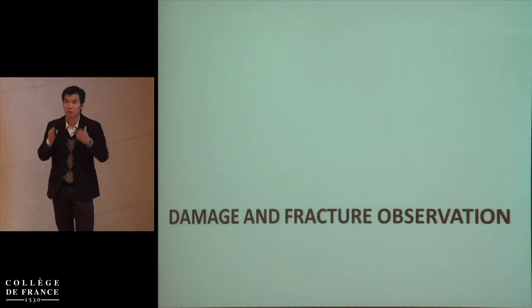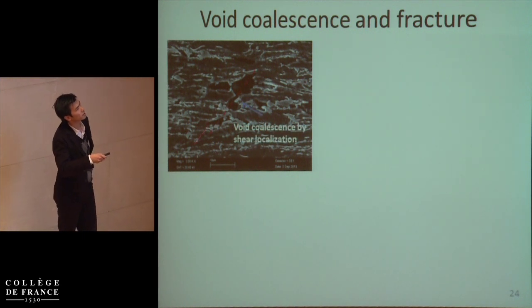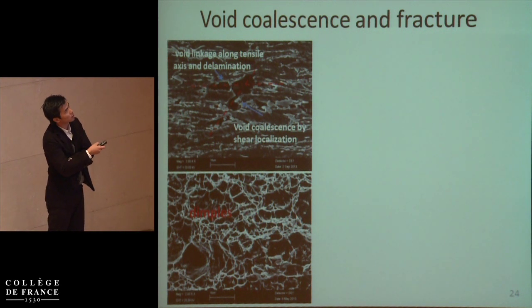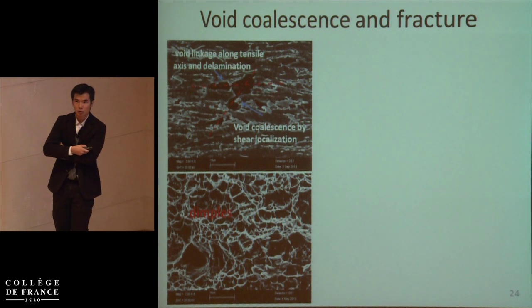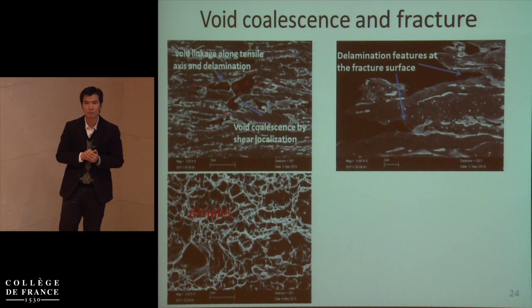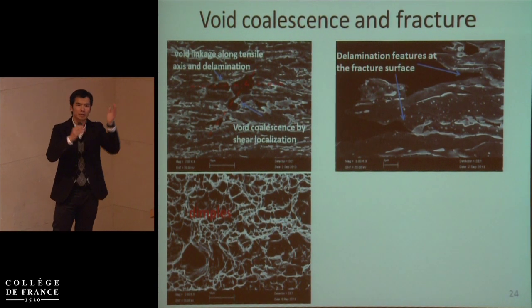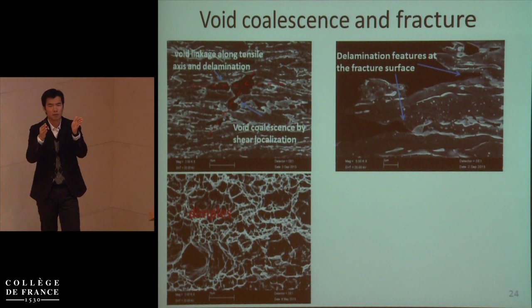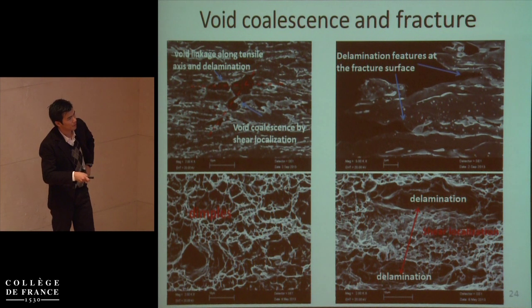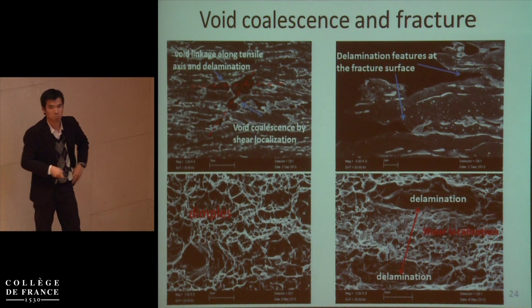With this fact, it is not enough to understand why fracture strength is improved, so I do damage and fracture observation to find out the mechanism. We observe void coalescence by shear localization, which leads to dimples on the fracture surface, and also void linkage along the tensile axis. This leads to delamination — and we can observe features of delamination on the fracture surface. Referring to the Brown-Embury criterion, this kind of delamination can be important in ductile fracture because if the size of the elongated defect is larger than the critical width, the critical distance between defects can be quite large for final instability. From the fracture surface we can observe the delamination here, here is the shear band indicating final instability, and notice the width of the shear band is more than 20 micrometers.